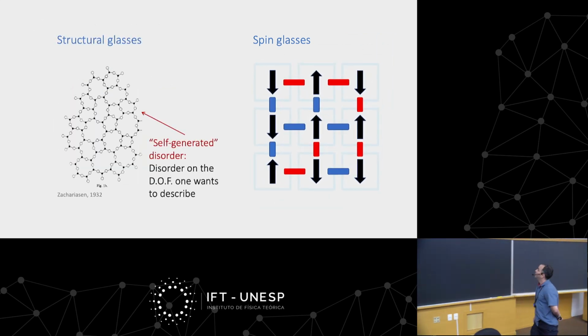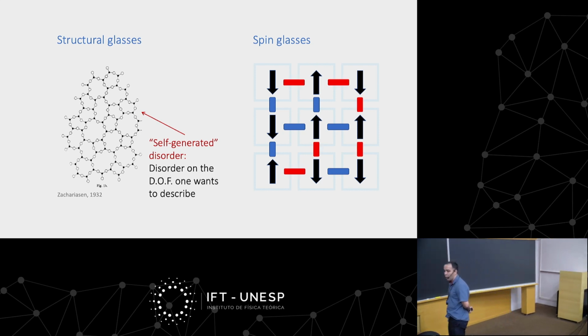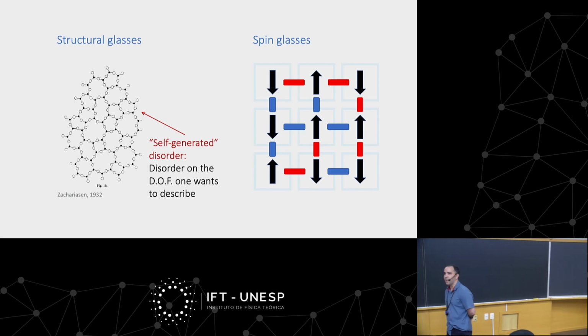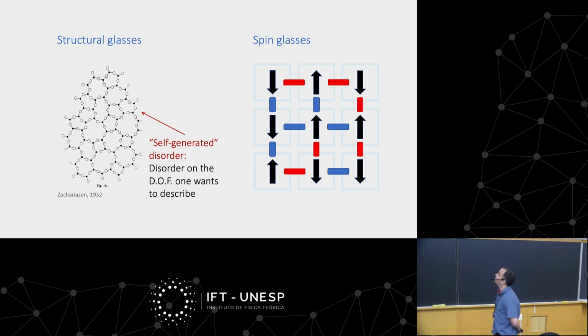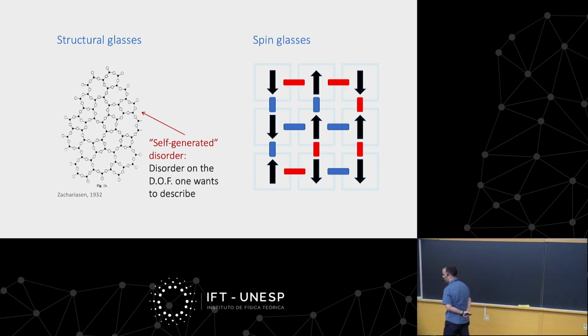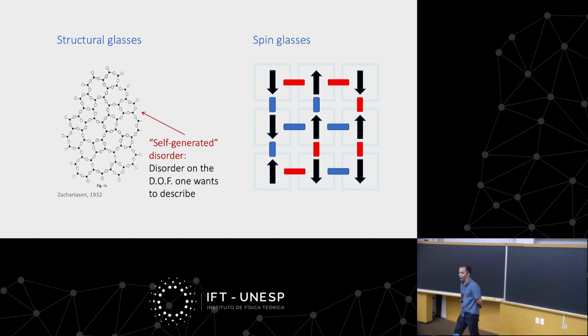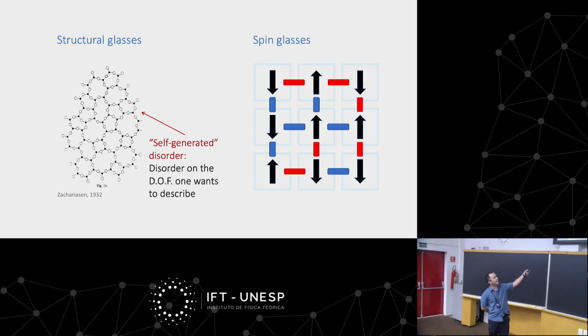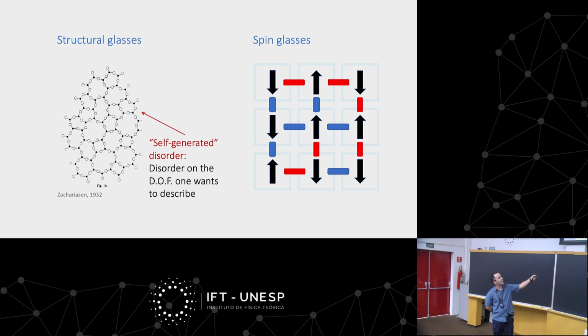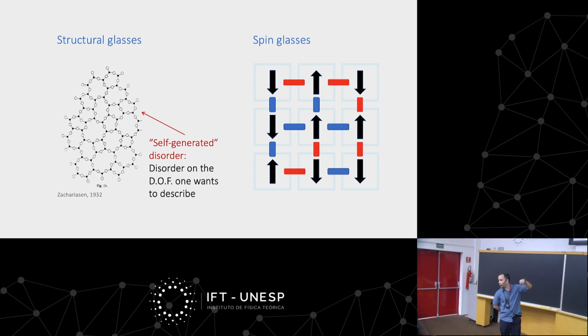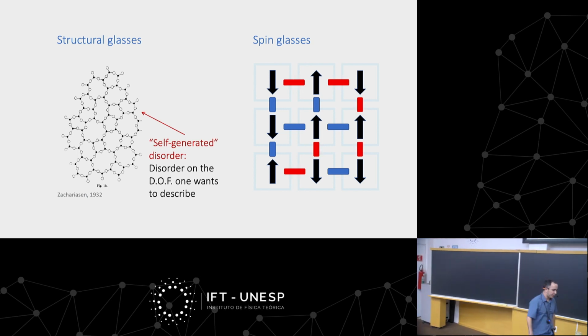Now, these are spin glasses, and back in the day, there was this hope that you could use something like a spin glass model to try to understand structural glasses. And here I'm giving an example of a structural glass. And very quickly, people realized that this was really not the case. I mean, the structural glasses were different in important ways. One of them is that, for instance, this disorder here is self-generated. And by this, I mean, the disorder is on the degrees of freedom, the positions that you want to describe, for instance, using statistical mechanics. Whereas here, the disorder is separated from the spin degrees of freedom, for instance. That's one of the reasons why these things are so different.